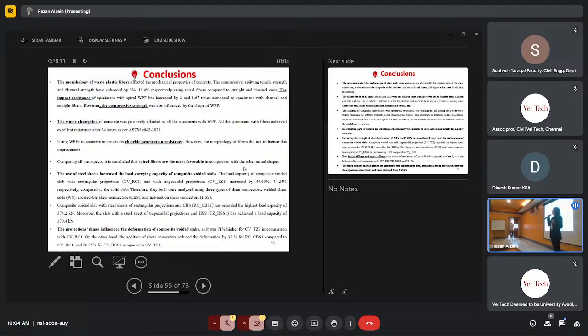So at the end, we can say that the results of the research show that the morphology of waste plastic fibers plays an important role in the performance of concrete, particularly the spiral fibers yielded the best results. We can say that the novel composite slabs presented in this research are very effective structural systems, especially with shear connectors that were designed also for this type of slabs. We have noticed improvement related to load carrying capacity as well as ductility, with the cross-part shear connectors providing the best results.